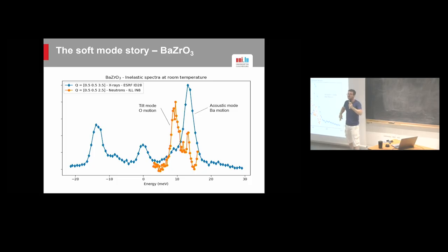I didn't make the calculation exactly on how long the spectra take, but I dare say you would have one order of magnitude between the X-ray spectrum and the neutron if you want to cover the same energy range, give or take. And in terms of sample size, I was mentioning our crystal here is really small by neutron standards, so pretty challenging. For X-ray, what they want is essentially something suitable for single crystal diffraction, so something like a lamella of 20 microns or something like that, depending on absorption. So this is much, much, much easier to prepare. So that was another soft mode.